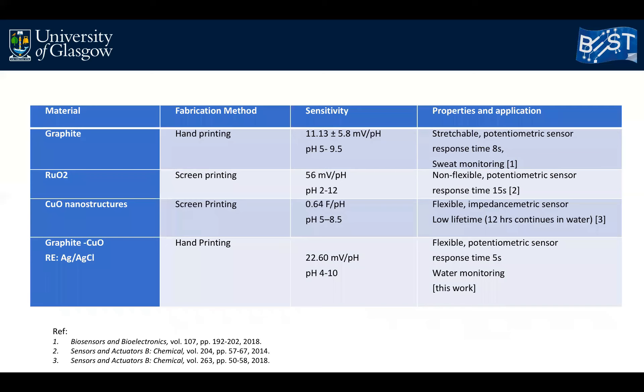This table shows a comparison of the fabricated pH sensor with other graphite-based sensors and ruthenium oxide, which is another metal oxide. As you can see, the sensor fabricated in this work can work in a wider pH range compared to graphite-based pH sensors or pure copper oxide. However, ruthenium oxide-based sensors can work in an even wider pH range, although that sensor is not flexible and requires higher temperature processing, whereas the sensor in this work is flexible and fabricated at low temperature.